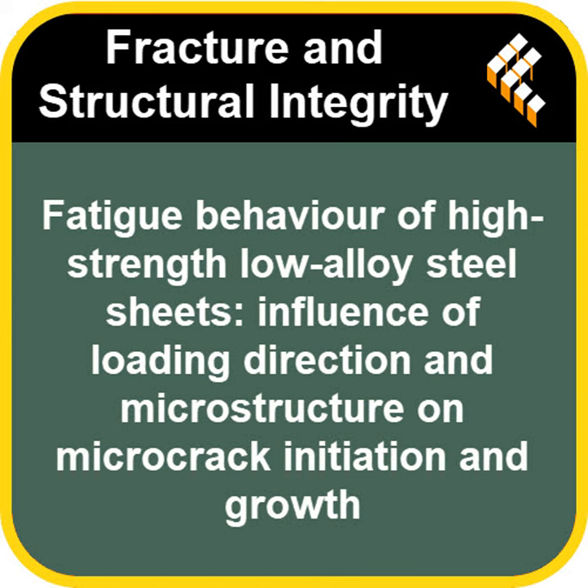What about TD? In TD samples, again at low strain, the cracks preferred to start right at the grain boundaries, intergranular cracking. This fits with what we saw earlier. Dislocations piling up and subgrains forming near those boundaries, weakening them. TD also just had more cracks overall, a higher crack density, and crucially, more of its cracks were already quite large, suggesting propagation was more aggressive right from the start compared to RD.